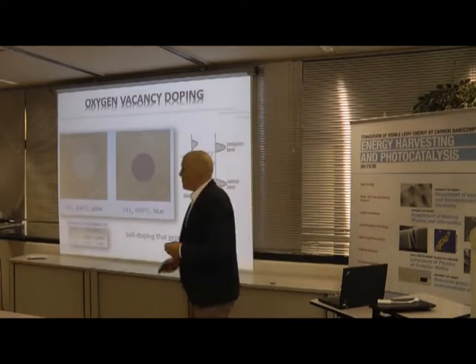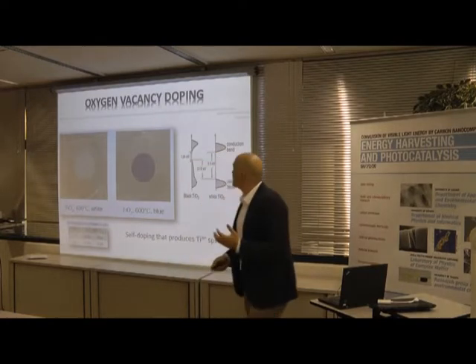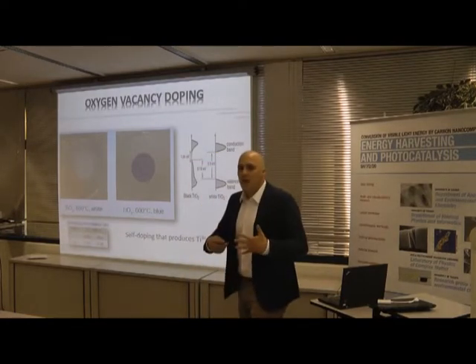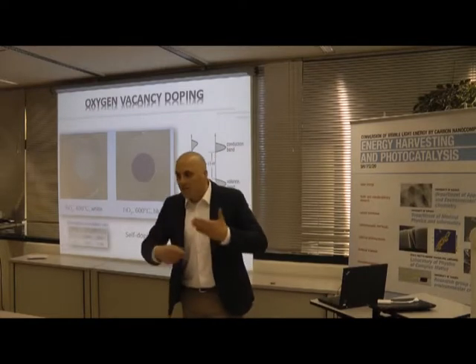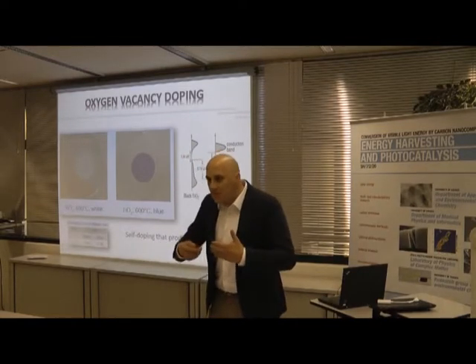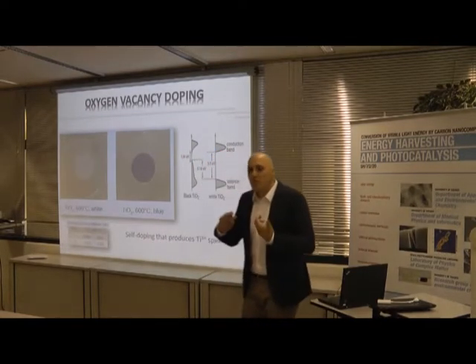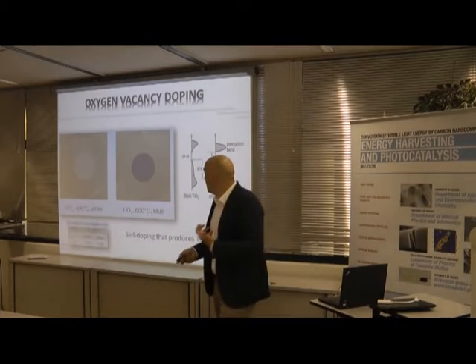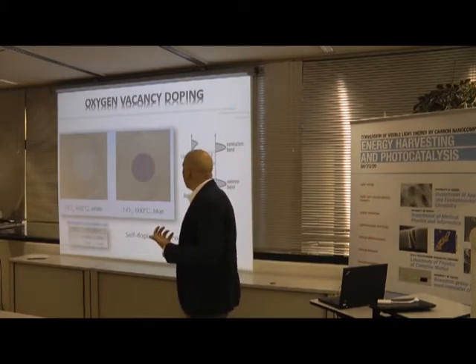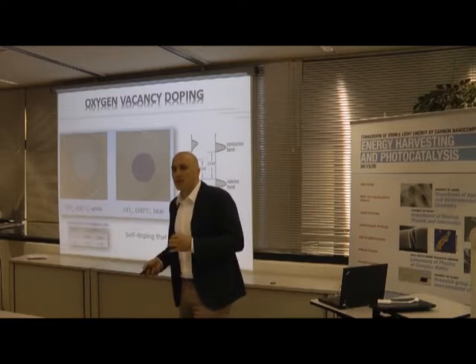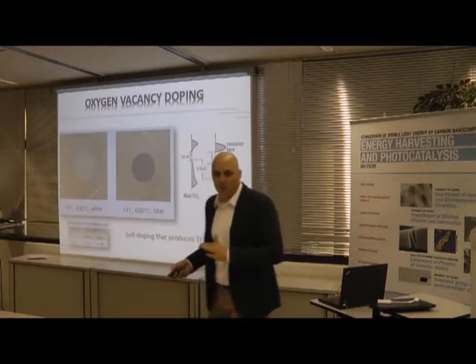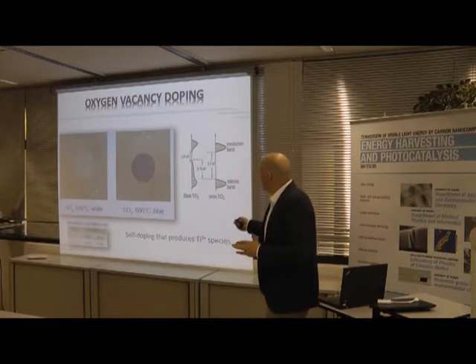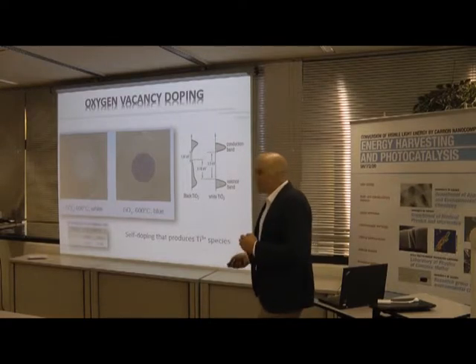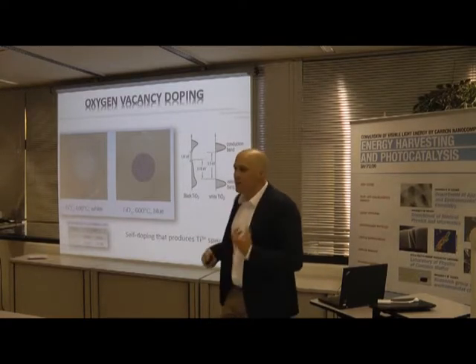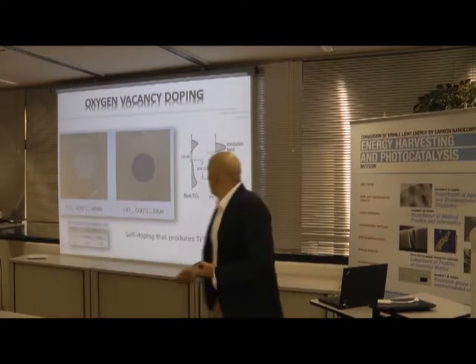The second method was the so-called oxygen vacancy doping. Since we have titanium oxide nanowires, a lot of atoms are on the surface. It means if we are able to remove some oxygens from the surface, then we render this titanium dioxide blue without any doping. This is only self-doping. We take out some oxygen and we create titanium 3+ species. And this will create these color centers in the material.